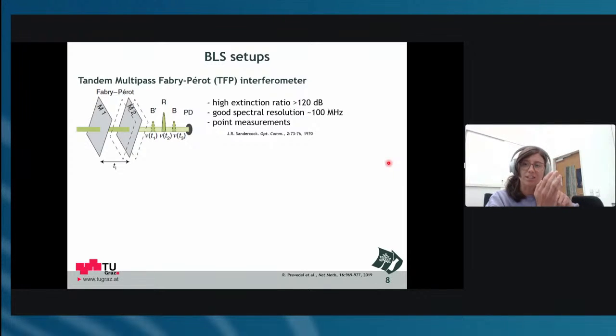So you take one position and then you measure on that one, and it's not the same as if you would do a Raman measurement. It's taking much longer time depending on your material. The more translucent your material is, the easier it is to do the measurement. But for example, the fibers take a lot of time, and it also depends a lot on the scattering geometry that you are using. And the principle of this interferometer is that it consists of two mirror pairs. So this is illustrated here as one mirror pair. You have M1 and M2. And by the distance of these two mirrors, I can determine the frequency range that I want to measure.